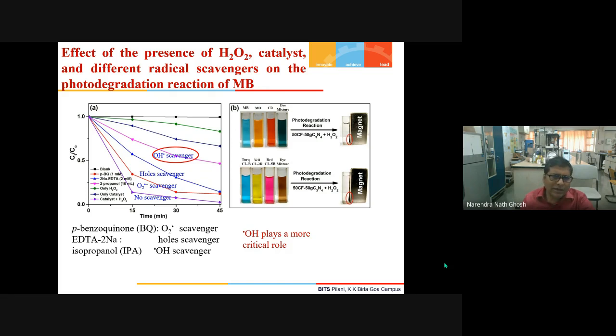Now, the green color, where we have taken only the catalyst, no hydrogen peroxide, we have seen that some amount of decomposition is happening. Then we took only hydrogen peroxide, and we have seen that some amount of decomposition is happening. But when we took the hydrogen peroxide and catalyst combination, the purple color, the graph shows the maximum amount of decomposition. 100% decomposition happens within 45 minutes.